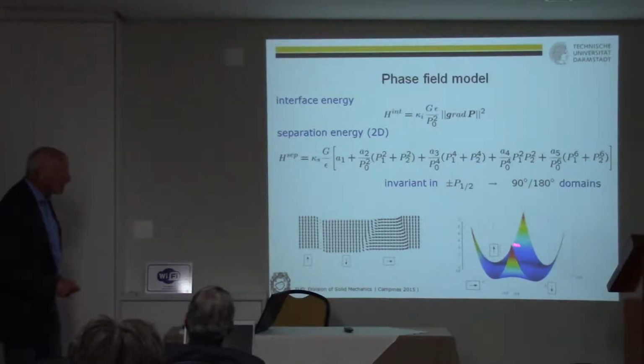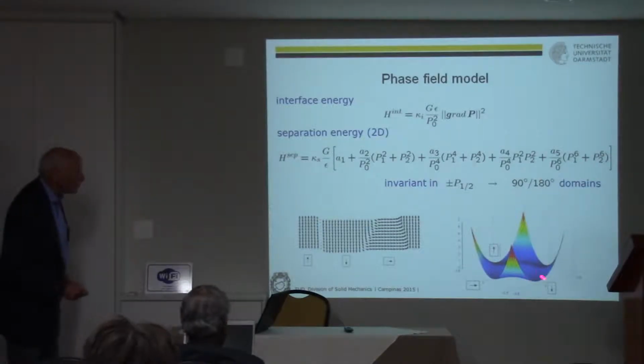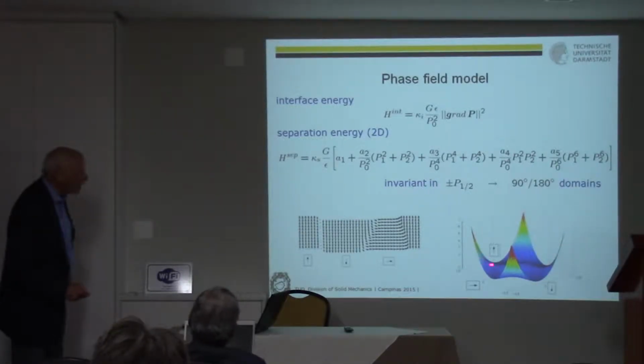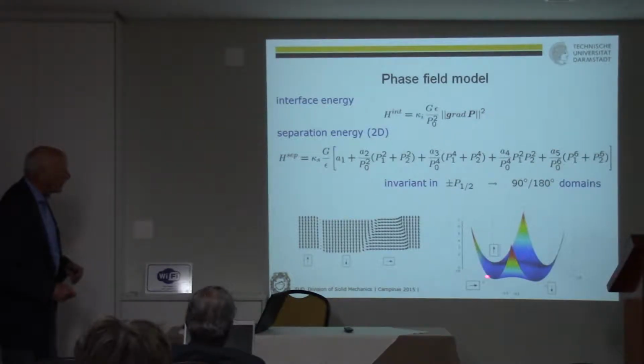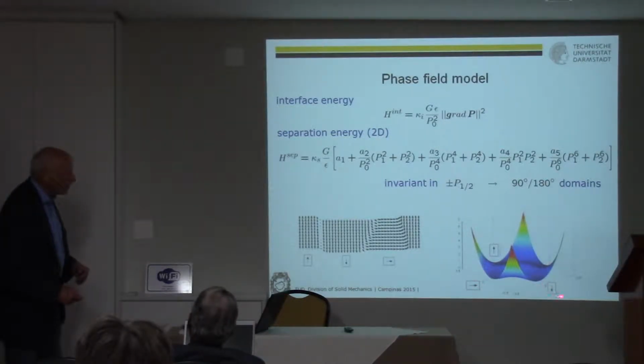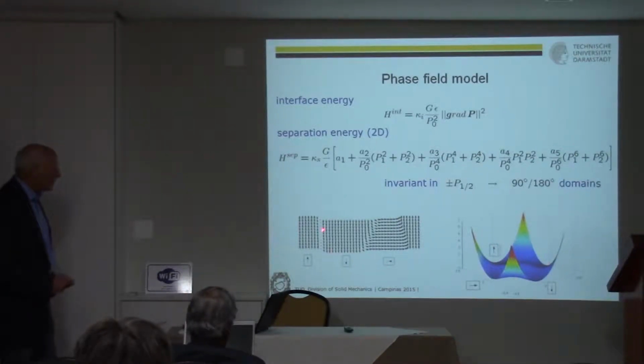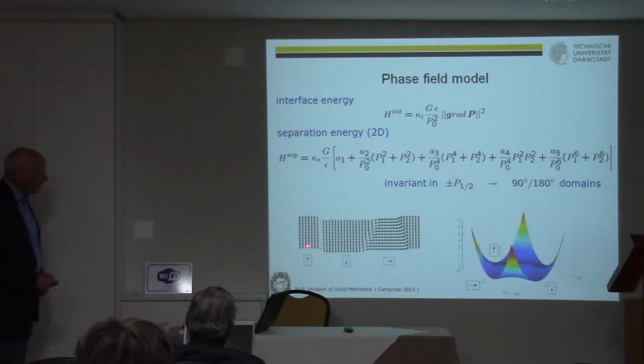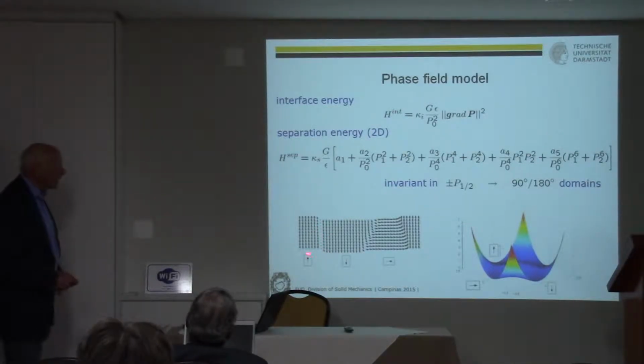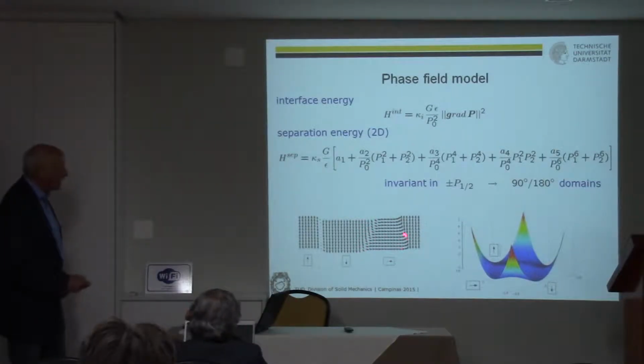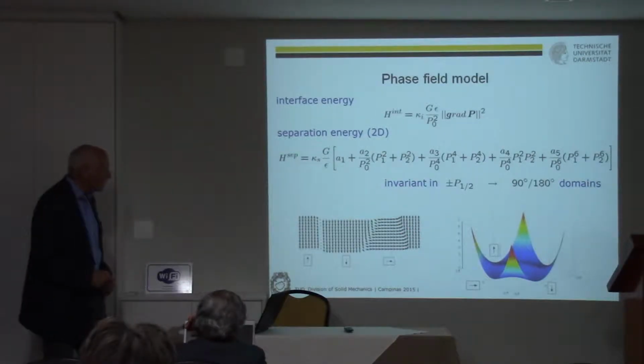Okay, and here this function, the separation energy, is in some sort plotted, and where the minima are, these are equilibrium positions, and they characterize certain polarizations here. As they are given here, the little arrows are the direction of the polarization. And here this is a 180-degree domain wall. Here you see a 90-degree domain wall. And again here, a 90-degree domain wall.